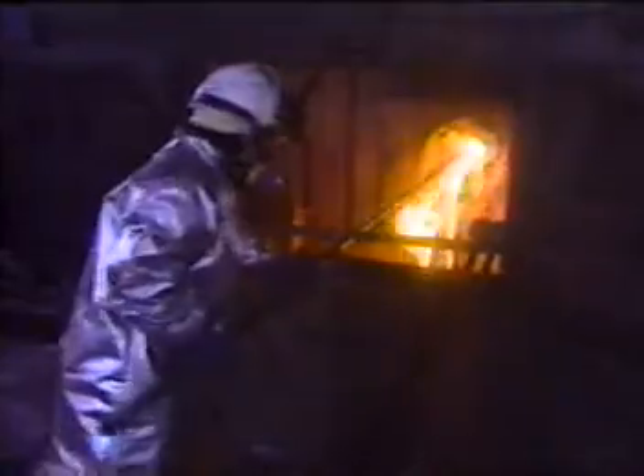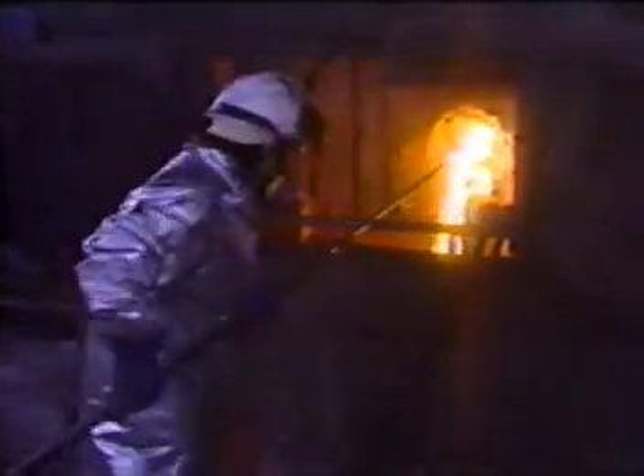At the opposite end of the reactor from where the feed was introduced, the molten bath at 2,200 degrees Fahrenheit was placid. Slag, or iron waste, floated to the top and was skimmed off. It was later processed to recover the copper that came off with the slag. The bottom layer of the bath, the matte copper, was now 73% pure. It was tapped from the bottom of the furnace into waiting ladles, which were transported by overhead crane to converter furnaces, where further oxygenating drove off sulfur and slagged iron to produce 98.5% pure blistered copper.